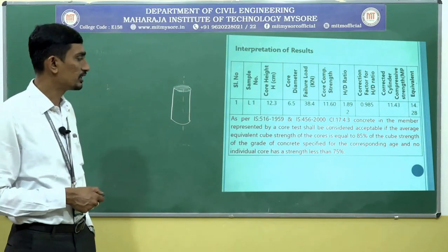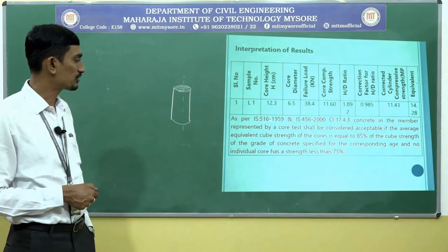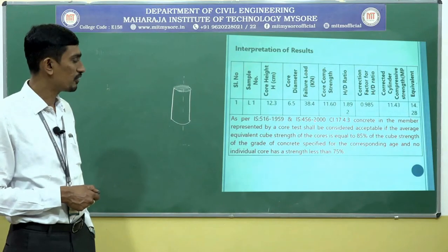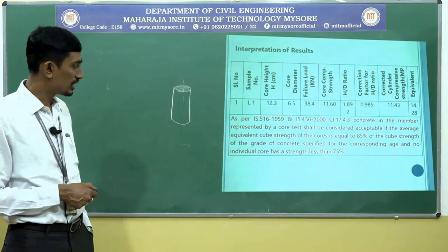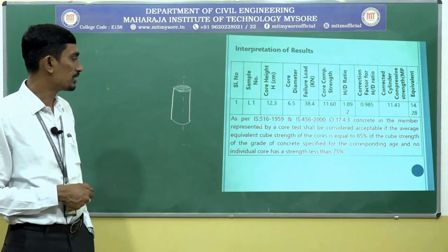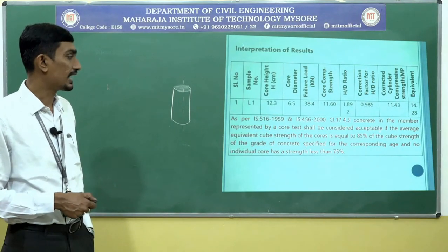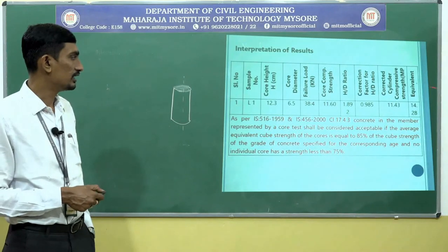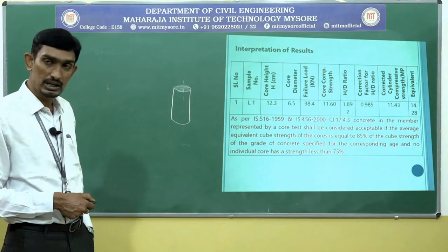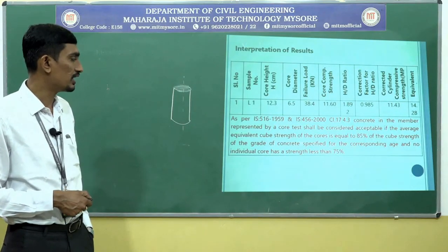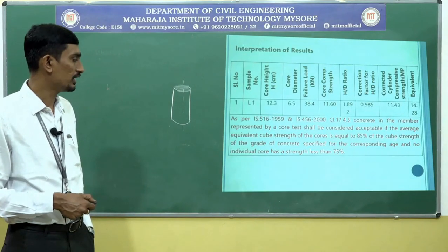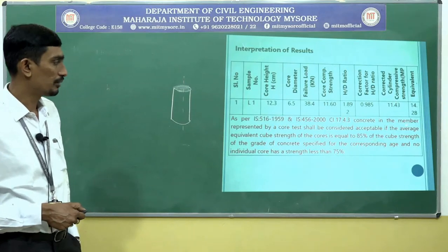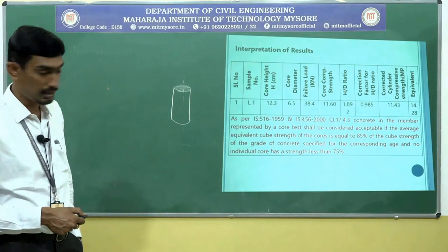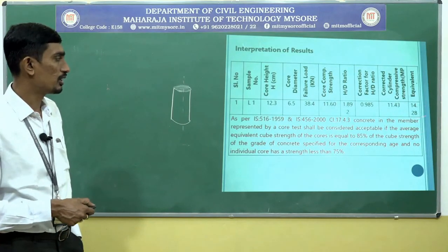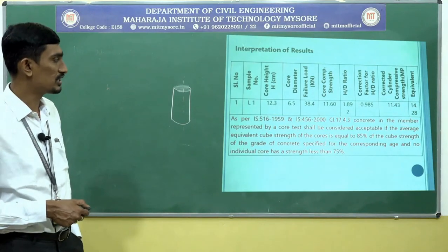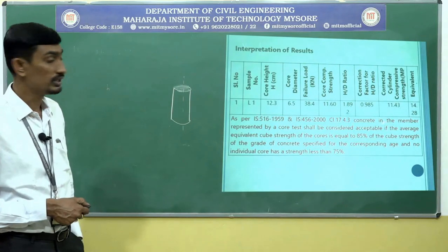And one particular sentence will be there in IS 456, as per IS 516-1959, this is the earlier code, and IS 456-2000 clause 17.4.3. It says, concrete in the member represented by a core test shall be considered acceptable if the average equivalent cube strength of the cores is equal to 85% of the cube strength of the grade of concrete specified for the corresponding age. I will repeat the sentence: here I have showcased one result, but if you have a number of results, the average of the equivalent cube strength of the cores is equal to 85% of the grade.